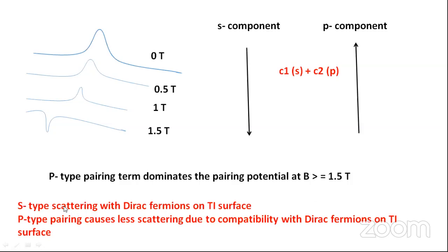So we would expect that an S-type pairing potential on the topological insulator would cause a higher scattering of the Cooper pairs, which could probably be the reason for this spiking. And as the S-type component decreases, the strength of this sudden spike decreases. And when the P-type becomes dominant over the S-type, there is a dip that we observe. This is what we are proposing. But then it does not end here. It gets a lot more complicated.